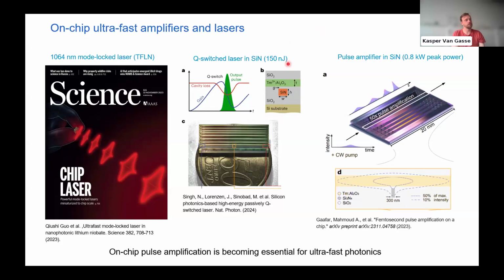Similarly, from DAISY, we have some very impressive results where people made a Q-switched laser. This is a tiny chip that can generate pulses up to 150 nanojoules. That exceeds a lot of tabletop systems even. So really impressive technology. And then finally, and this is the state of the art in ultra-fast optics on chip, people have also shown that you can make a femtosecond pulse amplifier in silicon nitride. And they can even amplify it up to about 800 watts of peak power. So very impressive, but still a long way to go compared to fiber amplifiers and other systems.